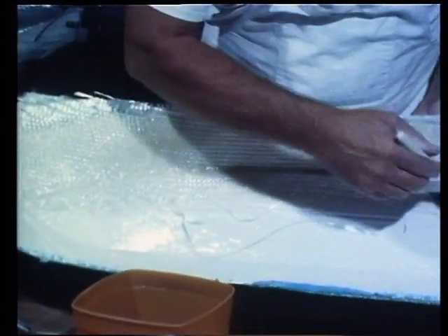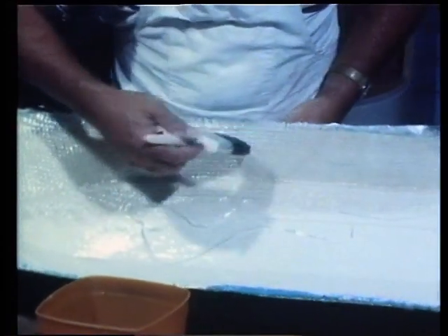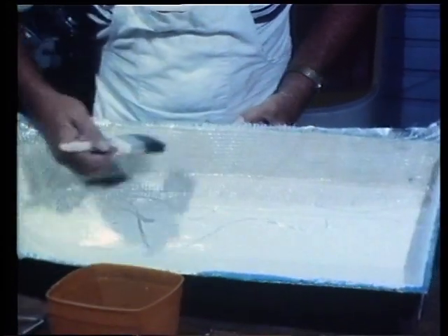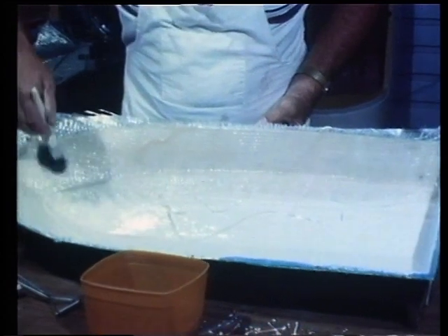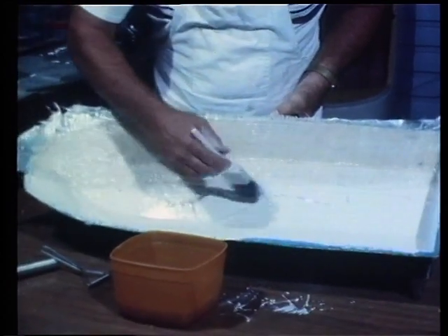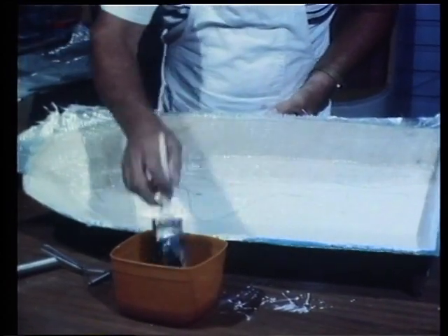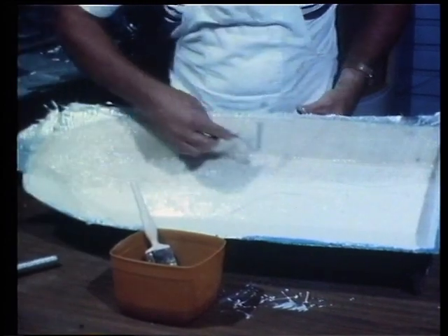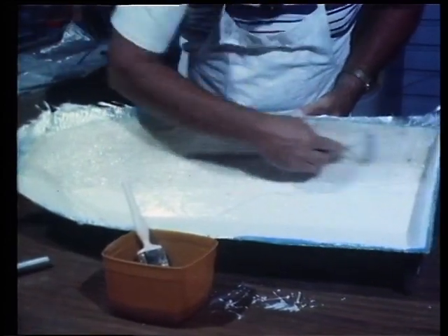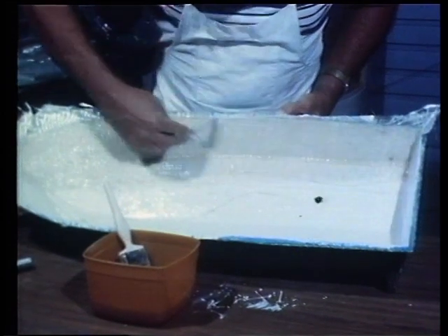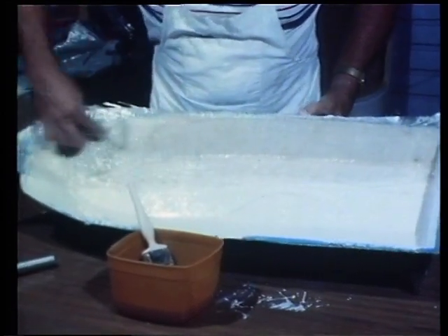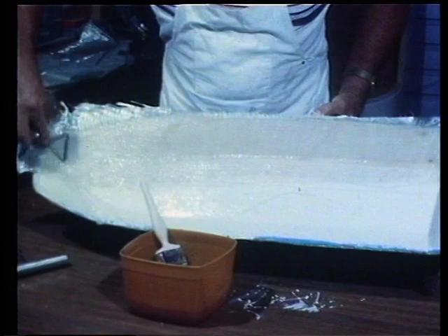It's possible to exercise quite a high degree of control over that glass even after it's wet out, once you have learnt the basic brush technique, the stippling technique. Now those strands sticking out there are not really important because the next layer will go over and cover them. Again, we use the compressor roller to work the woven roving and to press the roving down into the mat underneath it and help the resin to squeeze through.